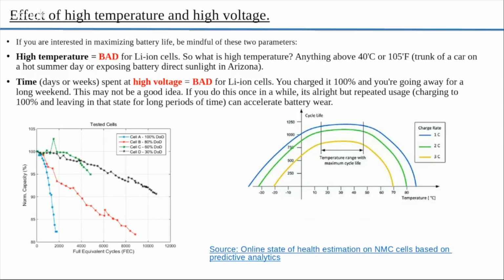It degrades the chemistry and it leads to parasitic reactions. And high temperature accelerates these parasitic reactions. It just makes it difficult for the lithium ions to diffuse. And what we see in this graph is the effect of temperature. So the ideal temperature to operate is between 20 to 40 degrees Celsius. And this is for different charge rates, 1C, 2C, or 3C cycles.